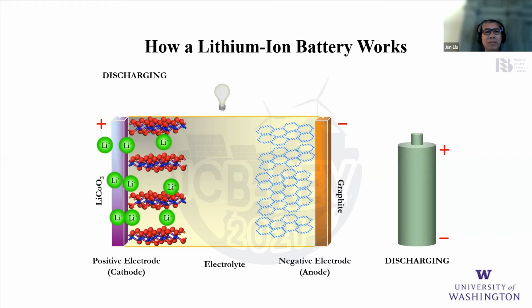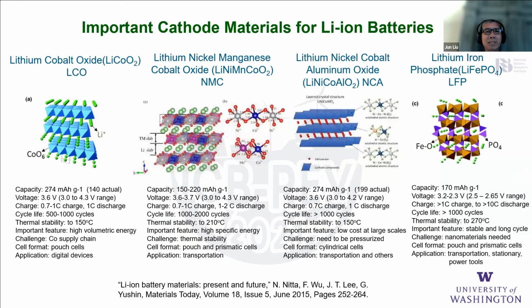battery. Now, some of the common cathode materials that we use include lithium cobalt oxide, which has been widely used in our cell phones because of the high volumetric energy density. Lithium iron phosphate is widely used in power tools and in energy storage because of structural stability. Lithium nickel manganese cobalt oxide, or NMC, or lithium nickel cobalt aluminum oxide, or NCA. Those are the 2 materials widely used for electric vehicles because of the high specific energy and light weight.